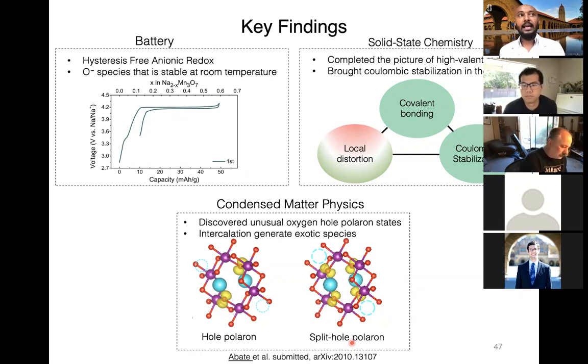But again, I think it's really interesting. Thank you very much. The main thing right now is, I discussed mainly the oxygen redox in this system, but you can also access the manganese redox in the system. I was carefully just looking at the oxygen redox because I wanted to understand that. But if you combine the manganese and oxygen redox together in this material, it is still low hysteresis, very reversible, and still has very high capacity that can be used currently in real technologies, maybe with modification of the surface and also improving the electrolyte in the devices.